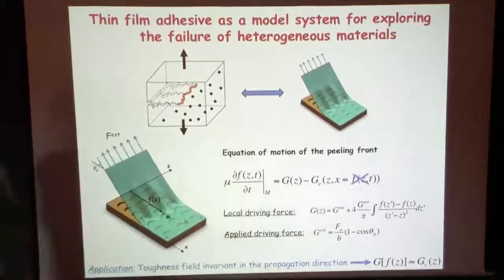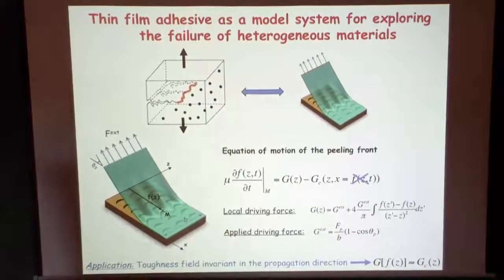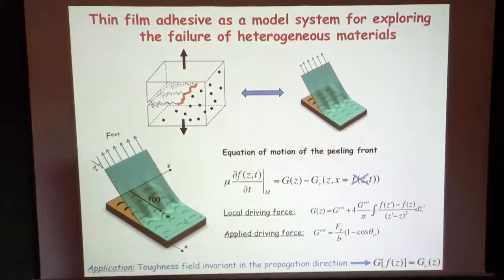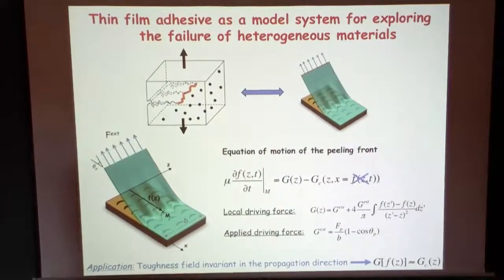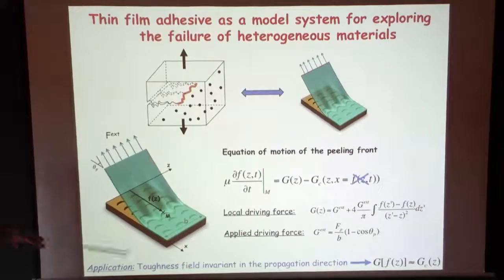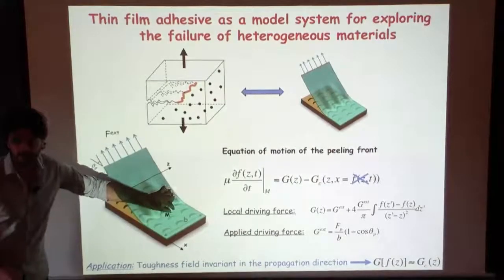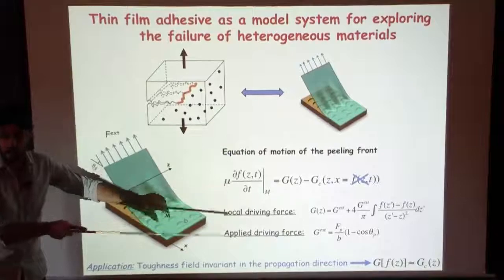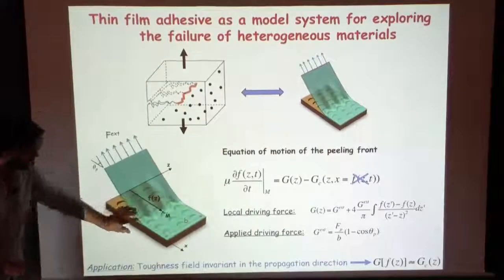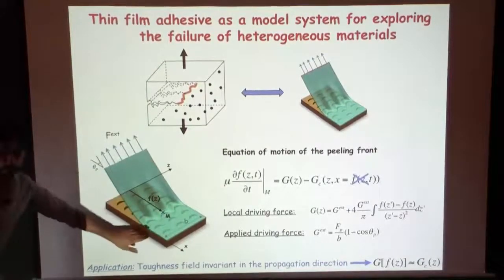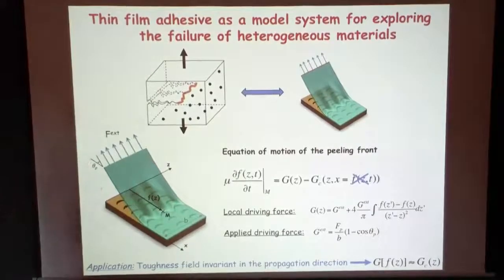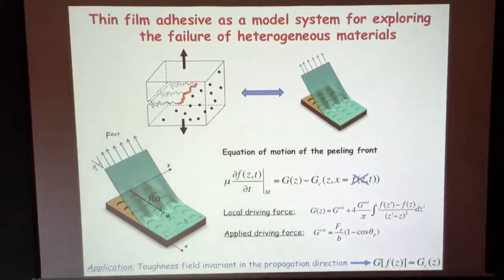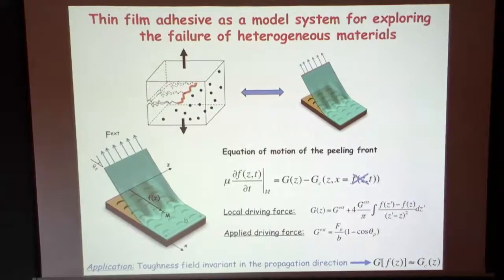What you have is the amplitude of the elastic term. You also have differences in the cutoff. I don't talk about the cutoff, but we started to discuss it. If you have a perturbation of the order of the thickness, this doesn't work anymore. And if you have a perturbation of the order of the bending length, the radius of curvature, you have other effects. So the differences are in the cutoff and in the amplitude of the terms, but not in the non-local term. So this 4 is non-local.